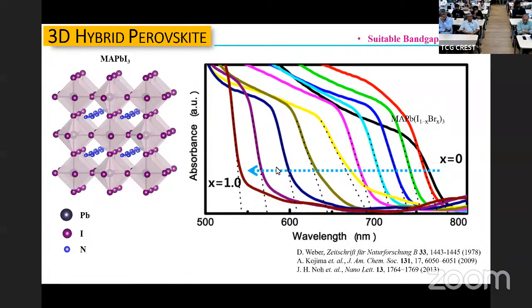What we are doing is making the MAPbI3 compound and replacing iodine systematically with bromine. And you can see that the band gap, this sharp rise, is systematically changing, starting from 1.5 electron volts to greater than 2 electron volts, which means that the band absorption edge is shifting through the visible range, right from red all the way to somewhere near green. And then by bringing chlorine in also, I can drive it all the way to blue, which means that the optical property of this material can be tuned right across the visible spectrum, and therefore you can get all kinds of optical properties and electro-optical properties.